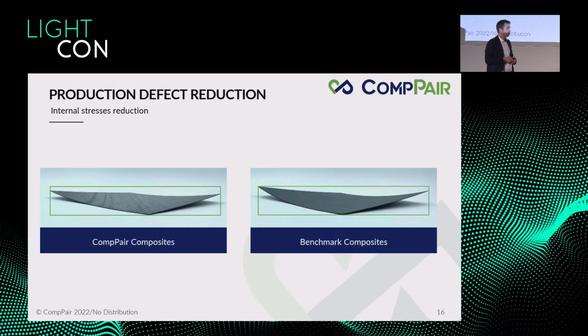In terms of internal stresses as well, what you see here is typically we've played around with really asymmetric layups, and out of the production you have really the composite that is completely bended. But what you see with CompPair composites is that this is reduced. And this is of interest because we reduce the internal stresses in there.